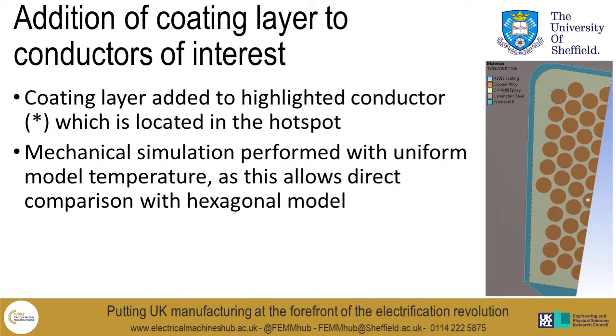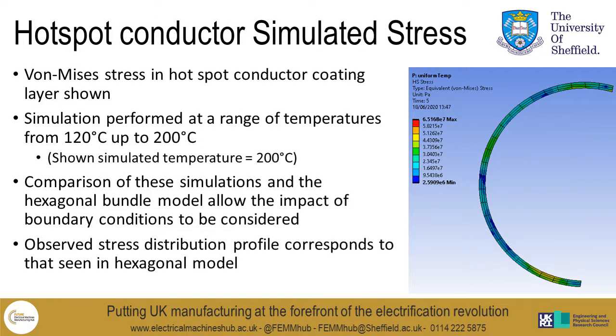So based on this conclusion, we've added the conductor coating layer to that conductor, as can be seen. The position of it is located by the asterisk. We then perform mechanical simulation, but in mechanical simulation we assume a uniform model temperature. This was done to allow direct comparison between the hexagonal models and this one. So this then shows the stress in that coating that I've just highlighted. We performed simulation at a range of temperatures from 120 degrees up to 200, and when we've compared these results to the hexagonal models, which I'll show the results of on the next slide, what you can observe from the form of the stress on this slide is that it follows a similar pattern to that which was observed in the hexagonal model, whereby the peak stress occurs in line with the adjacent conductors.